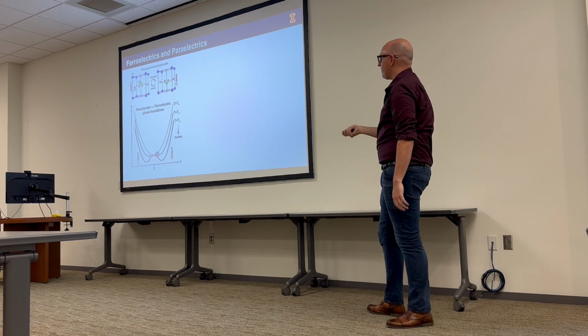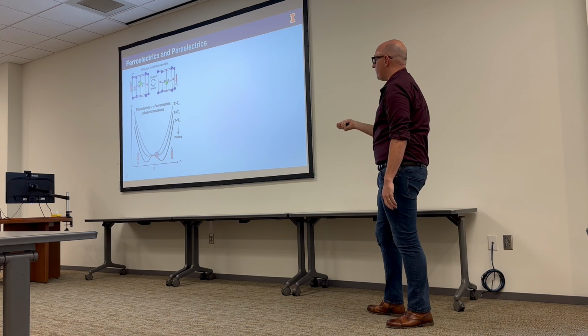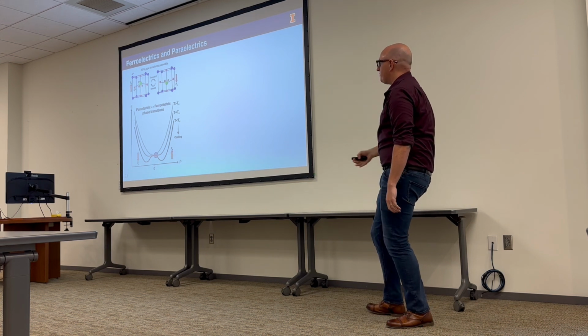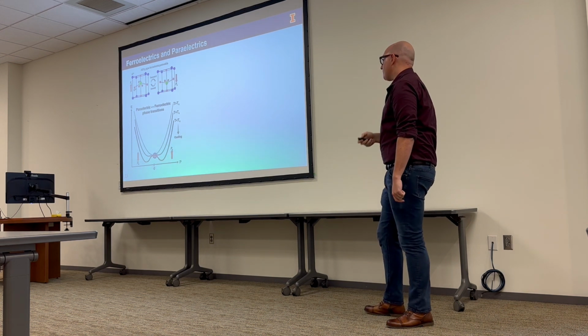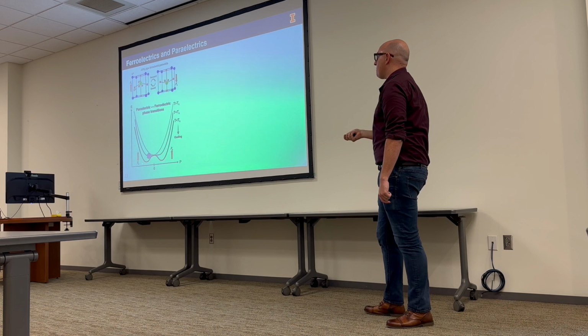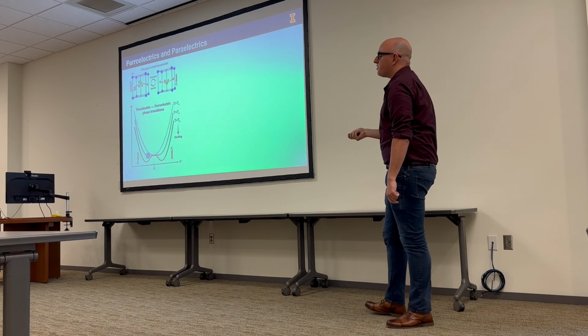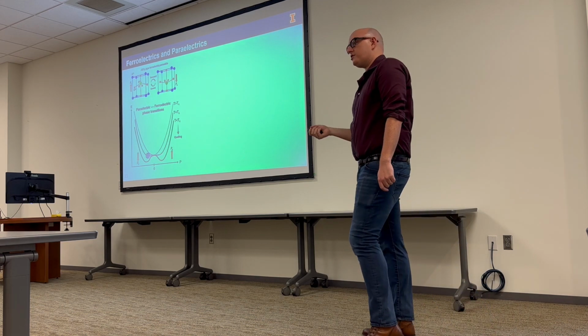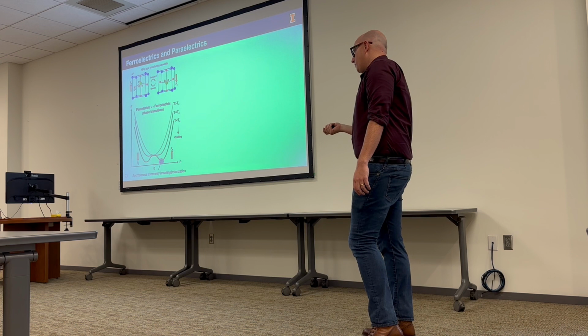It looks harmonic, so this is electrical polarization and energy. If I try to perturb it, I get this sort of harmonic response of the crystal. But as I approach this phase transition temperature and I cross over between an unpolarized state and dropping into one of these two wells, the energy landscape looks super flat, which means I can have drastic changes in the electrical polarization for basically no energy cost. And then of course, I cool down further and I drop into one of these harmonic wells again.